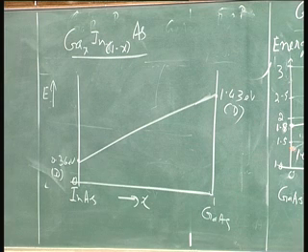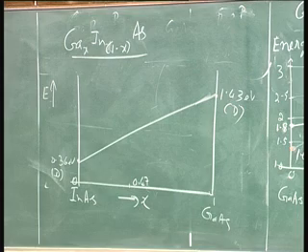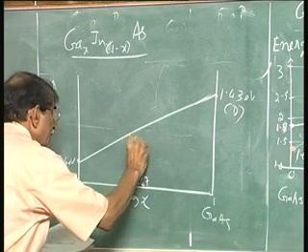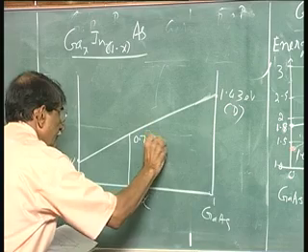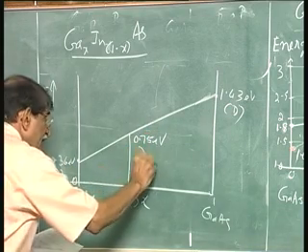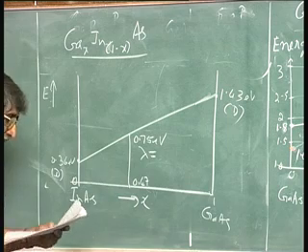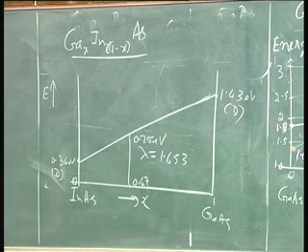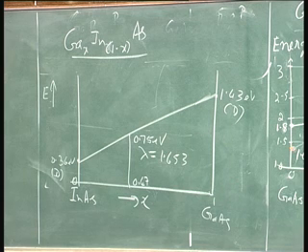Okay. So, for example, if you use this as 0.47, use that as 0.47, then you get around 0.75. Okay. 0.75. The wavelength corresponding to that is equal to 1.653. Now, what we want to point out here is, this is direct, not indirect.